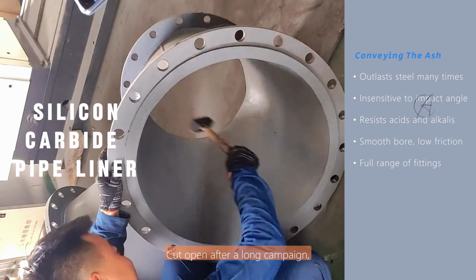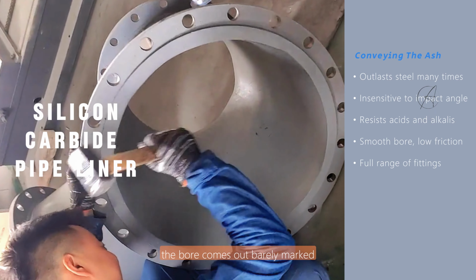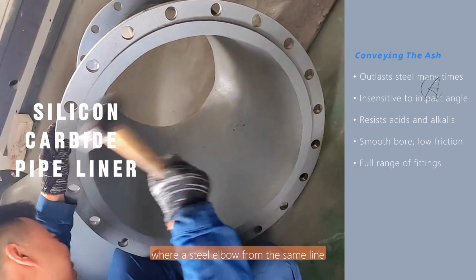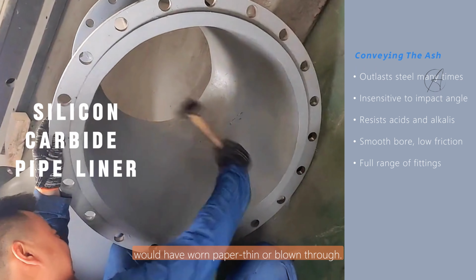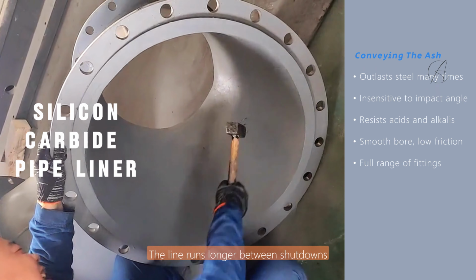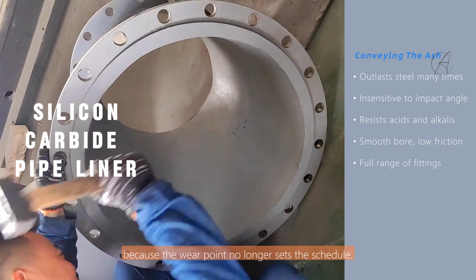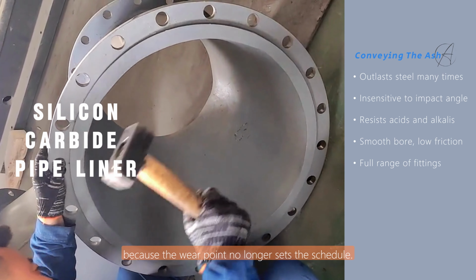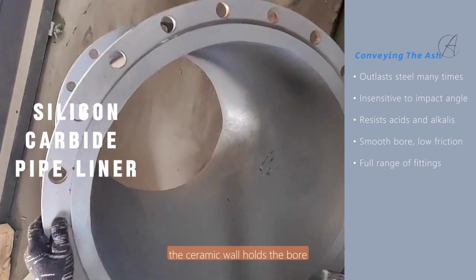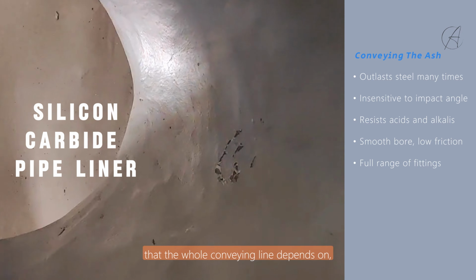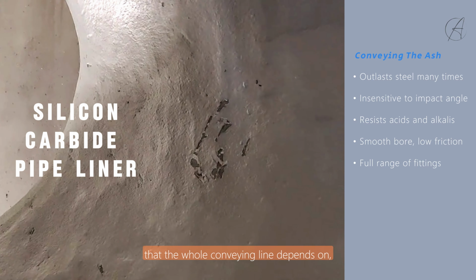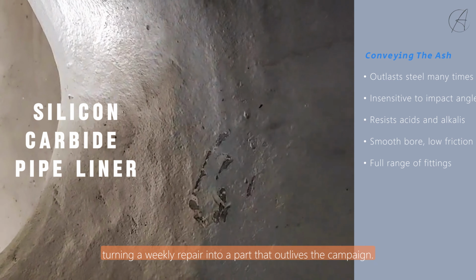Cut open after a long campaign, the bore comes out barely marked where a steel elbow from the same line would have worn paper thin or blown through. The line runs longer between shutdowns because the wear point no longer sets the schedule. Resolutely, the ceramic wall holds the bore that the whole conveying line depends on, turning a weekly repair into a part that outlives the campaign.